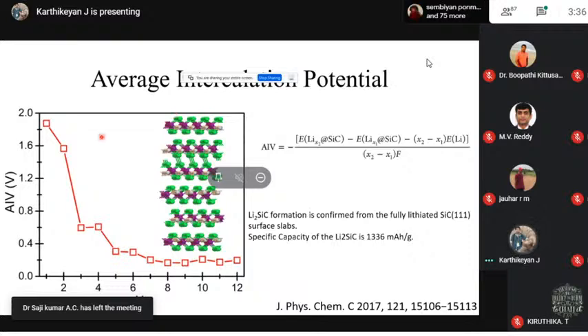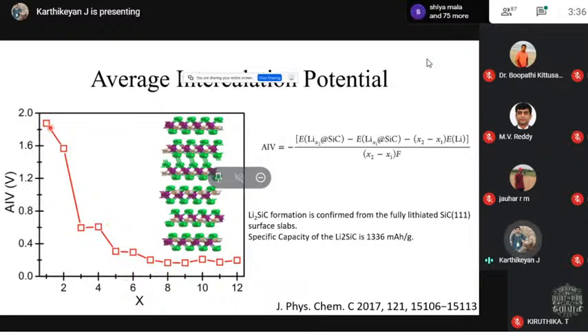If you add a lithium on top and bottom of the silicon carbide layer, it forms a very interesting structure of Li2SiC. The middle layer is graphitic silicon carbide. On top of the silicon carbide layer, we have one lithium, and the bottom has the second lithium. So this is actually Li2SiC layer formation. We have increased the number of lithium atoms. When you add a lithium on the surface, obviously it releases a lot of energy because of the lithium interaction with the surface undercoordinated atoms. But when you increase the number of atoms, it goes to the bulk of the silicon carbide nanoslabs, and the average intercalation voltage is really low. That shows it's a really good anode material.